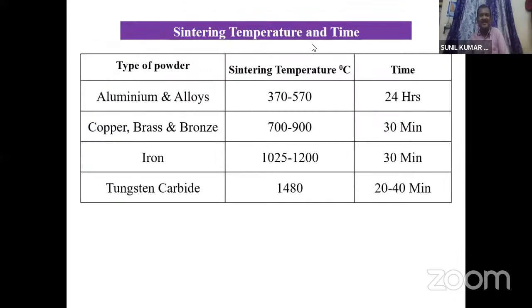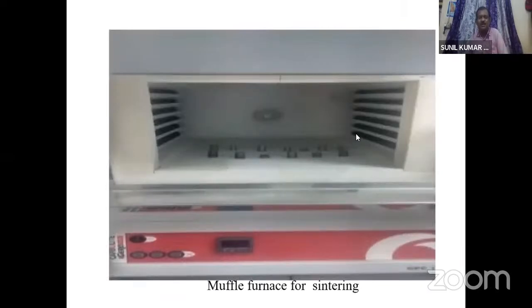Then coming to the sintering temperature and time table. Here, different metallic powders are listed, with the sintering temperatures chosen according to the type of metallic powder, and the sintering time. For aluminum alloys, the sintering temperature varies from 370 to 570 degrees centigrade, and the time is 24 hours. For copper, brass, and bronze, the temperature varies from 700 to 900 degrees centigrade, and the sintering time is only 30 minutes. For iron, the temperature is 1025 to 1200 degrees centigrade, and the time is only 30 minutes. For tungsten carbide powder, the temperature is 1480 degrees, and the time varies from 20 to 40 minutes. This is the sintering furnace, or muffle furnace, used for the sintering process.